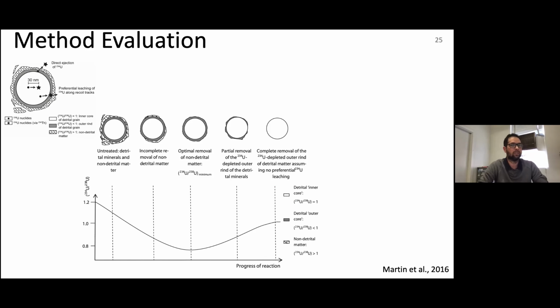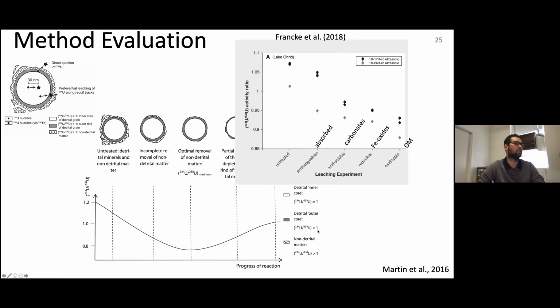if we run these analyses, we want to analyze the uranium isotope composition of our detrital matter. So we need to get rid of any authigenic material, organic carbon, and inorganic carbon in the sediment composition. There were other methods previously published by Tony Slab. We went back to find a bit of a faster and more effective method. And what you actually want to achieve by removing all the non-detrital matter from your bulk sediment is to see this decrease in activity ratios.